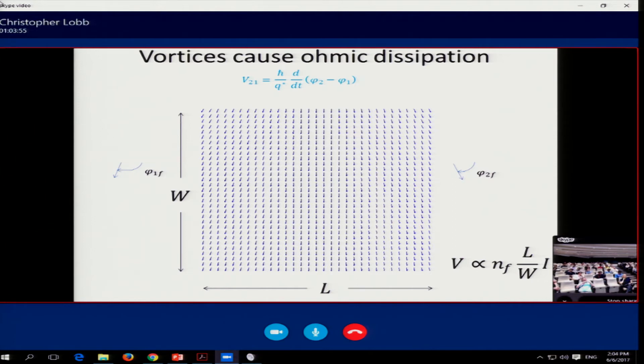It'll be proportional to the length over the width. And it will also be proportional to the density of free vortices. And this is at the heart of our measurements, any experimenter's measurements, of the Kosterlitz-Thouless transition. If we put a current on and detect a voltage, it means that there are free vortices present. If we know the constants, the material properties that I've left out, and the theory properly, it allows us to measure the free vortex density. And we can do that as a function of current, of magnetic field if we care to put one on. We can do it as a function of temperature. So this is our angle into this beautiful field, measuring things like you'd measure the value of resistance that you take out of the parts box in your lab.